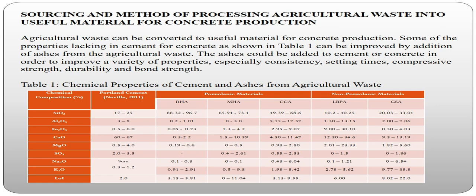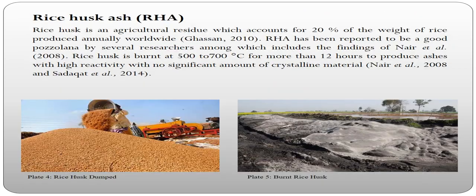Sourcing and method of processing agricultural waste into useful material for concrete production. Agricultural waste can be converted to useful material for concrete production. Some of the properties lacking in cement for concrete, as shown in table 1, can be improved by addition of ashes from the agricultural waste. The ashes could be added to the cement or concrete in order to improve a variety of properties, especially consistency, setting time, compressive strength, durability, and bond strength. Here is table 1. You can see some of the pozzolanic materials considered in this literature, in this review.